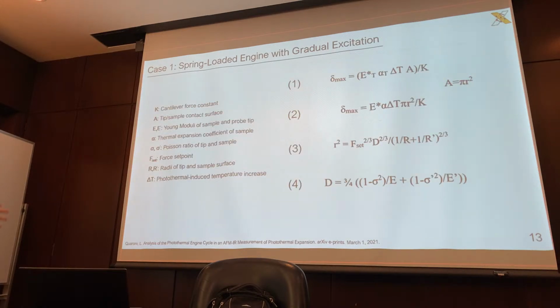In this case, they break down the fundamentals, and I won't spend too long on this slide, but I really wanted to dive deeper on some of these fundamentals, the things that actually affect how we can get a stronger signal in AFM-IR. In the case of K, this is the actual cantilever force constant. So this is the force that, if you simply placed your probe on the sample, the sample experiences from your tip, with no added force. So essentially this means that the stiffer the spring, the less deflection we're going to see. For smaller spring force constants, which usually corresponds to a softer spring, you're going to become much more sensitive to those changes in deflection, or changes in thermal expansion, I should say.